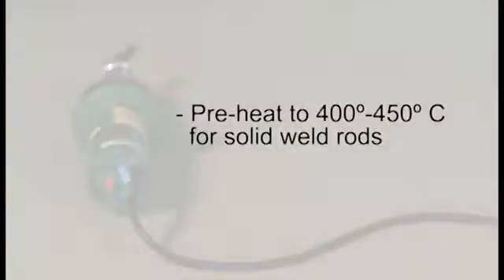Solid weld rod can also be used for commercial vinyl sheet flooring. When welding with solid weld rod, the same procedures are used as welding with the pattern weld rod, with the exception of the heat gun temperature. The temperature of the heat gun should be set at approximately 400 to 450 degrees centigrade for the solid weld rod. This picture shows an improperly welded seam that would typically be not acceptable to the end user.